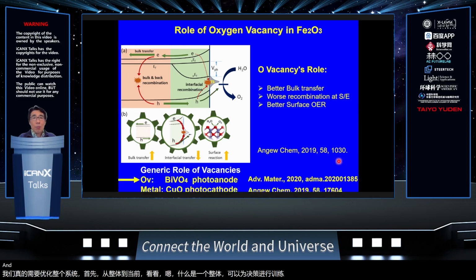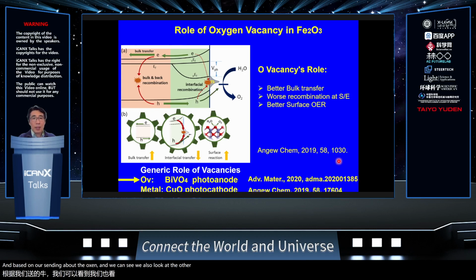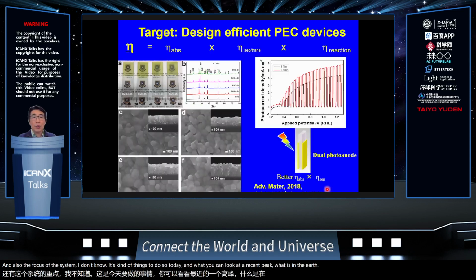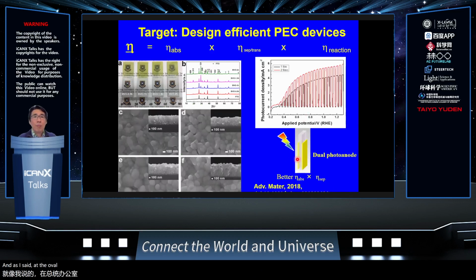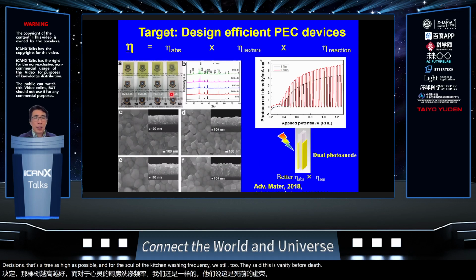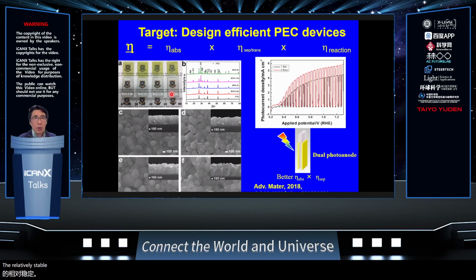Based on our understanding of the oxygen vacancy, we also look at other systems, like the photoanode system and also the photocathode system. I don't have time to introduce them today, but you can look at our recent paper if you're interested. And as I said, the final target is still to reach an efficiency that is as high as possible. For the solar to hydrogen conversion efficiency, we still choose this material because it's relatively stable and high performing.